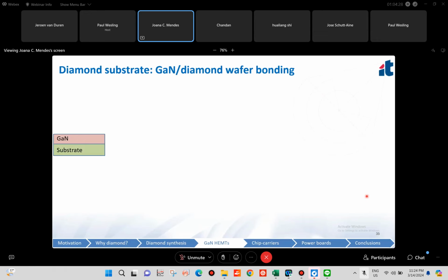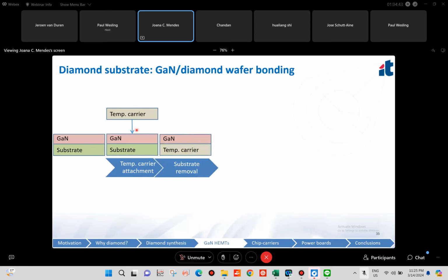We can also replace the substrate by bonding gallium nitride and diamond wafers. And we start with the same procedure. We have the GaN on substrate, GaN on silicon substrate, for instance. Again, we attach a temporary carrier, and again, we remove the substrate.